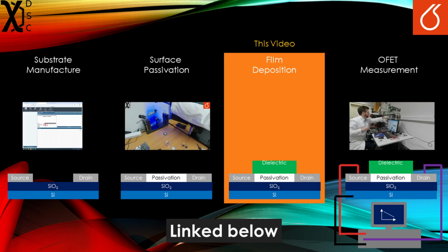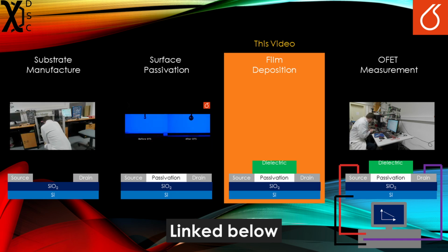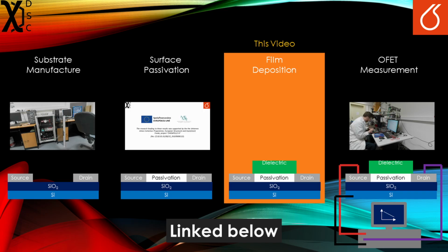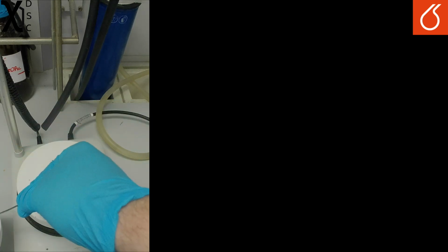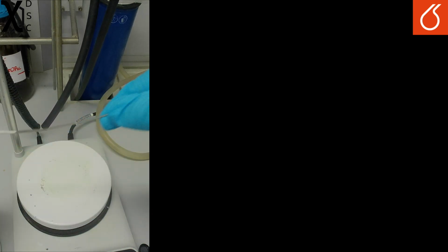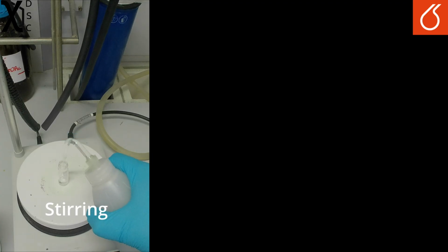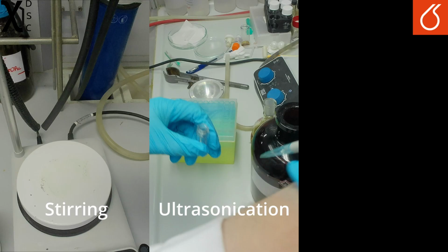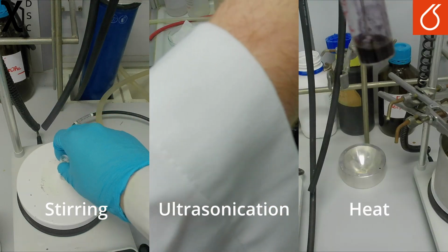There are quite a few methods of deposition, including vacuum deposition, spin coating, drop casting, inkjet printing, and sputtering. Here I will focus on drop casting, spin coating, and blade deposition. The first step to these methods is to dissolve the compound into a suitable solvent. The compound should be mixed with solvent until it turns transparent, indicating dissolution. Sometimes this will take some time and require stirring or ultrasonification. Additionally, heating may be used to help the compound into solution.